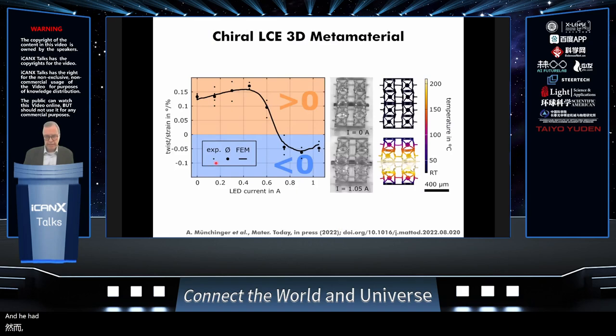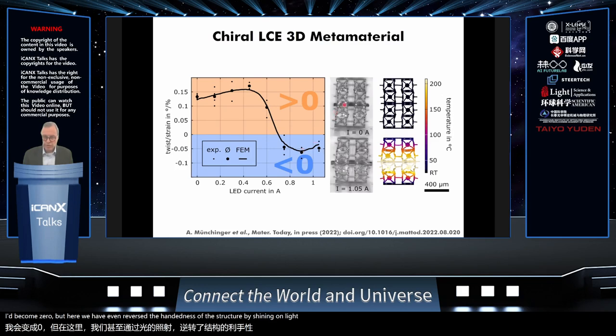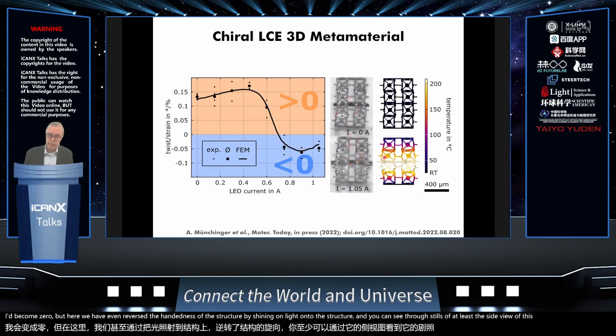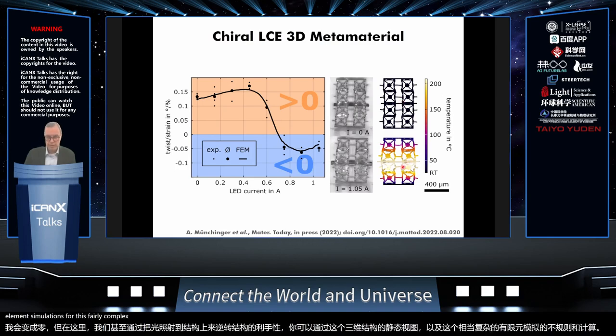And here you see the measured twist per strain. So the physics here is we take the sample, we push on it. Because it is chiral, it twists a little bit. And depending on the handedness, this twist is positive, or it becomes zero. Or here we have even reversed the handedness of the structure by shining on light onto the structure. And you can see two stills of at least the side view of this three-dimensional structure together with theoretical calculations with finite element simulations for this fairly complex structure on the right-hand side.